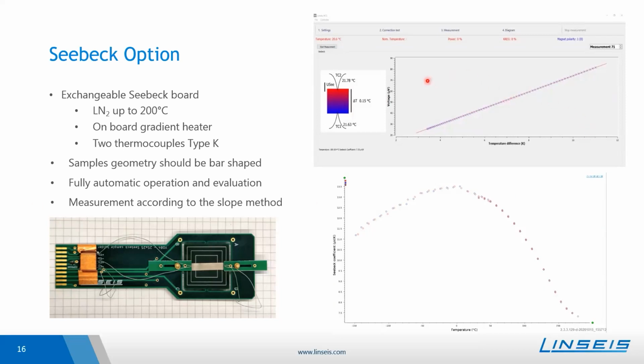The Seebeck voltage is recorded along with the temperature gradient, while the gradient heater, which is located in the back side of the sample holder, has its power linearly increased, and in the end we get a curve like that. You see the thermal voltage as well as the sweep of the temperature difference. The duration of such a measurement sweep is typically about 30 to 90 seconds, so it's a very fast measurement. The slope can then be used to determine the Seebeck voltage over temperature, and we find the Seebeck coefficient with respect to temperature using the slope method. Also, since the measurement is so fast, the offset drifts have very low impact on the result.